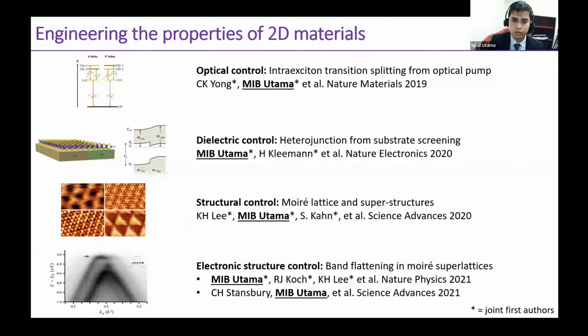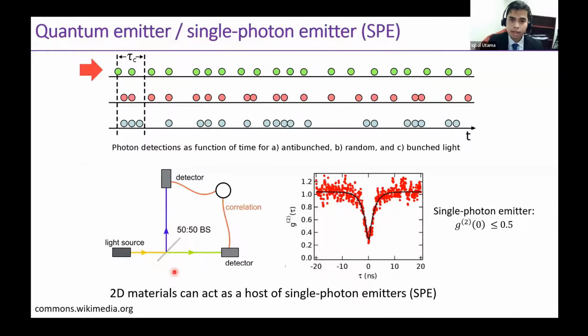Another implication of the formation of these Moire fringes is a strong modification of the electronic properties of the sample, which we can then visualize using various types of synchrotron-based X-ray experiments, as shown here. This modification of electronic behavior because of the interlayer twist angle can be dramatic, and you can observe new electronic correlation phenomena from this two-dimensional material system. But the property of interest for the talk today is called single photon emission.